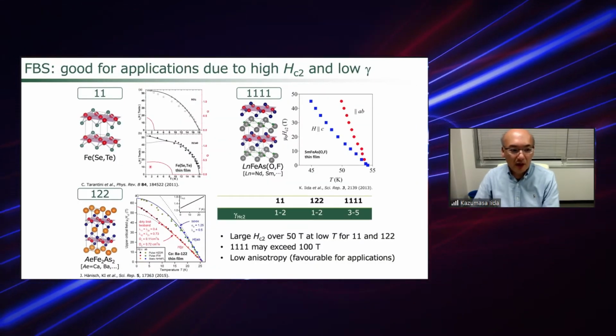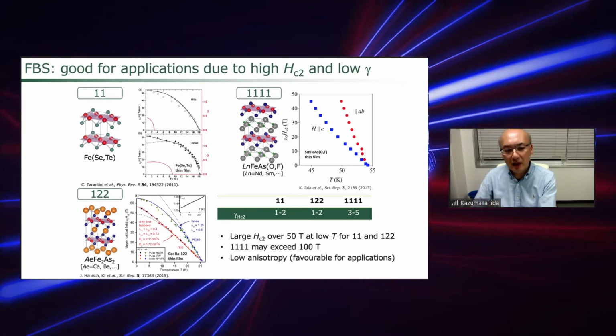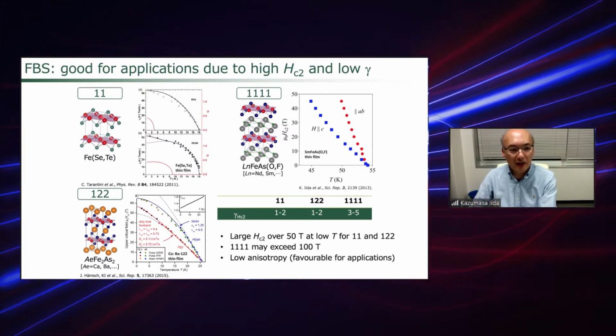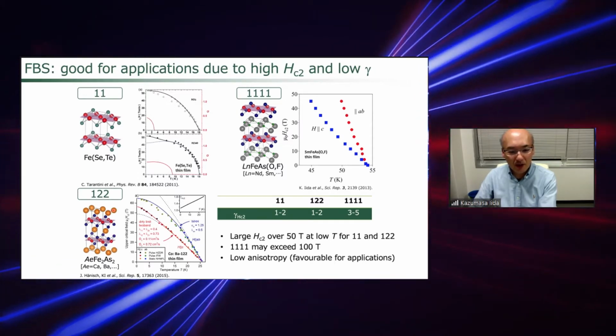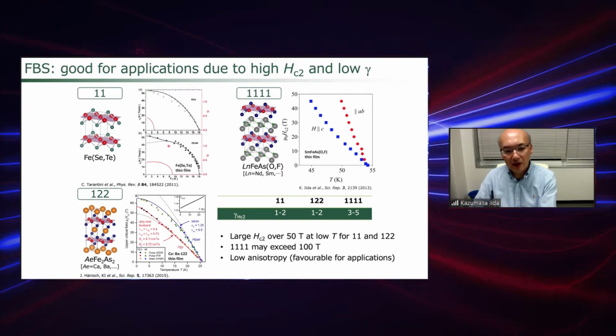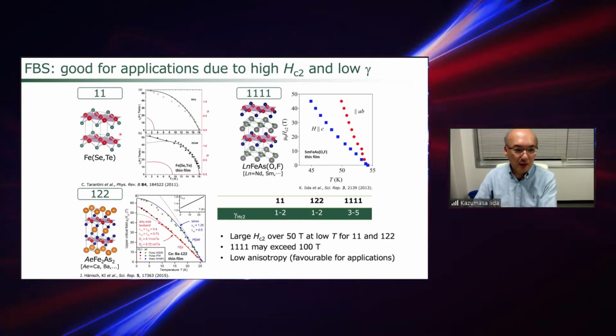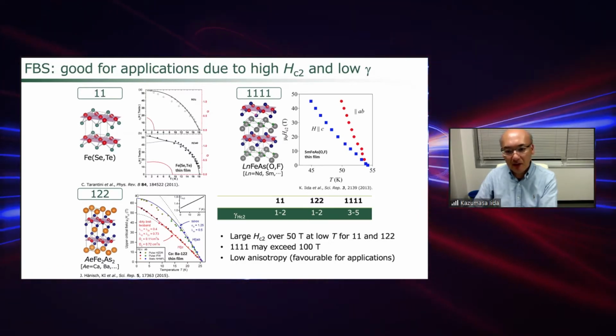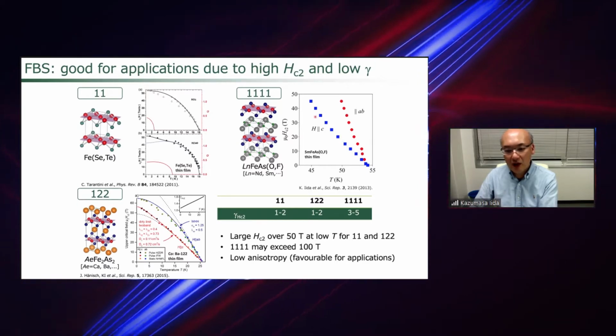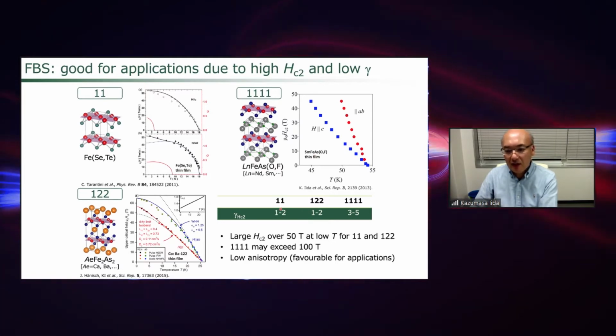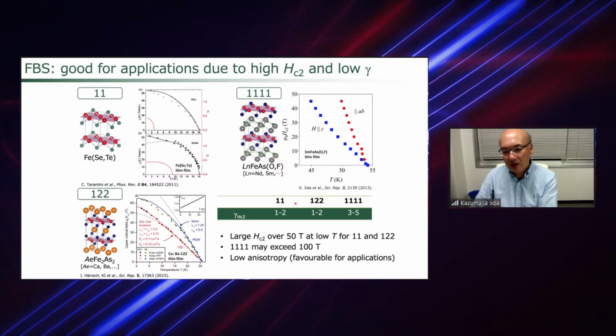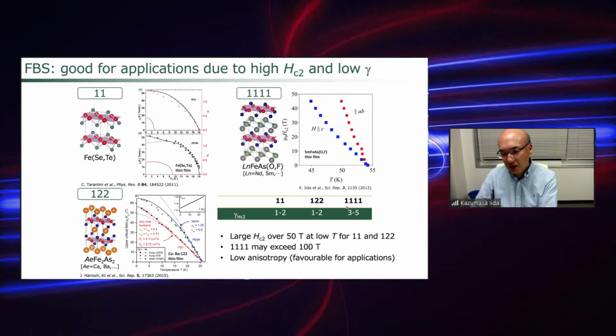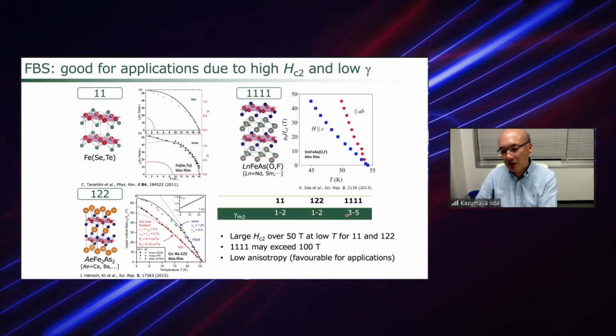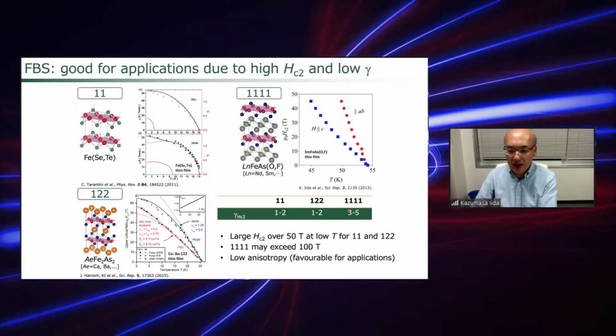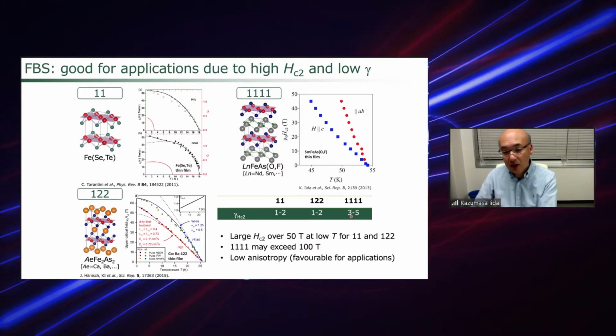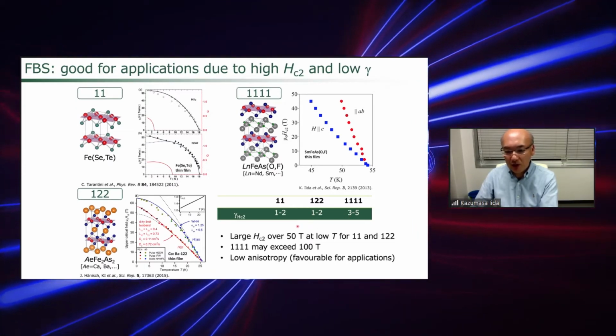In addition to the good grain boundary properties, the iron-based superconductors show a very high upper critical field. Here is iron selenium telluride 11, and this is cobalt-doped barium 122, and also the 1111 systems. You see that the upper critical field at low temperature exceeds 50 Tesla for 11 and also 122. For the 1111 system, the upper critical field exceeds 100 Tesla, which is quite large. Additionally, these materials show very low electromagnetic anisotropy, between 1 and 2 at low temperatures. The 1111 system shows a slightly larger value, between 3 and 5, but compared to the bismuth-based cuprate superconductors, this anisotropy is much smaller and comparable to YBCO samples. So these properties are very good for applications.